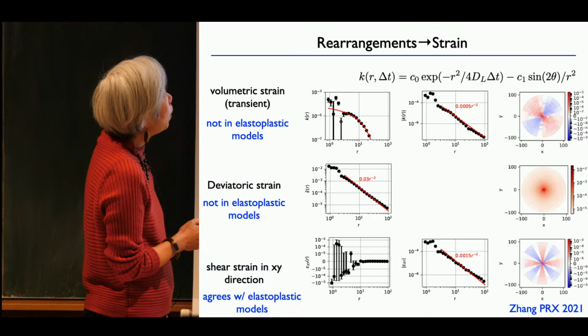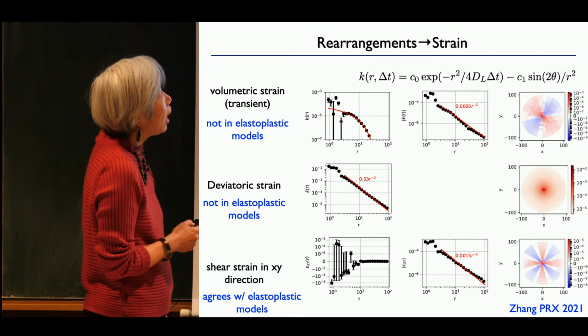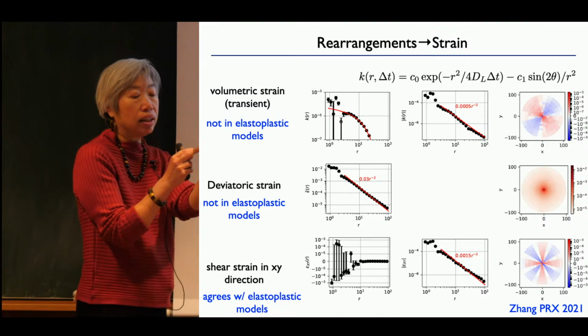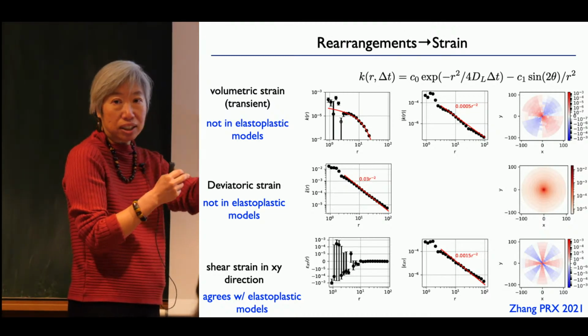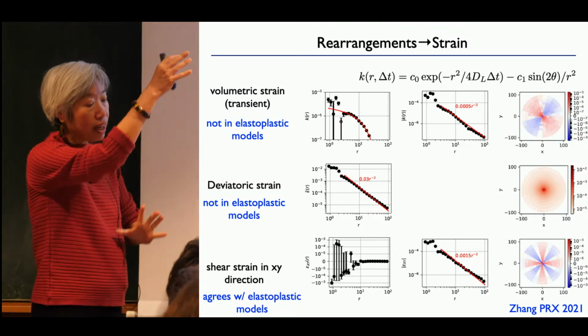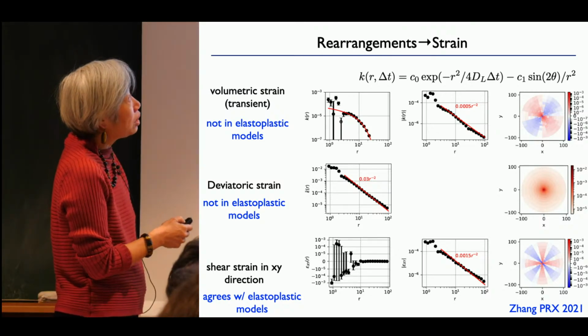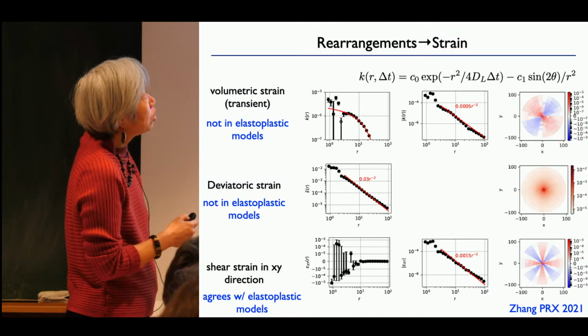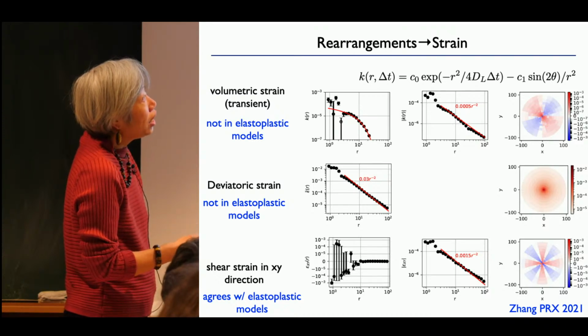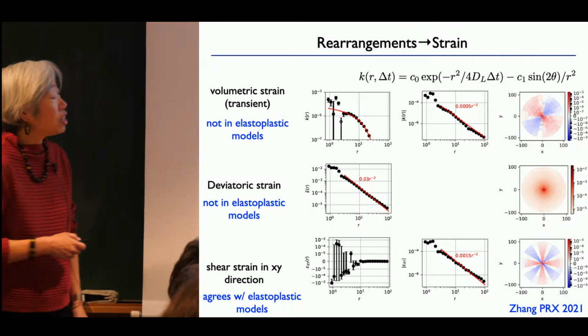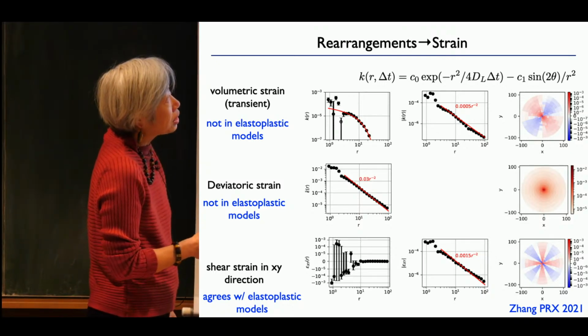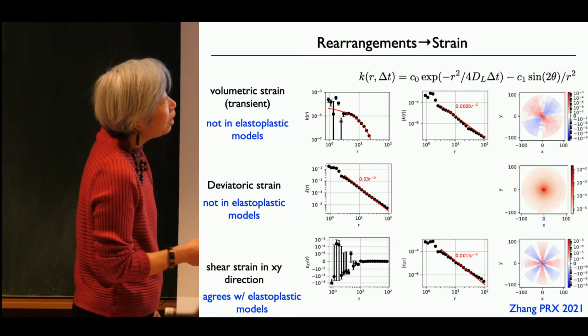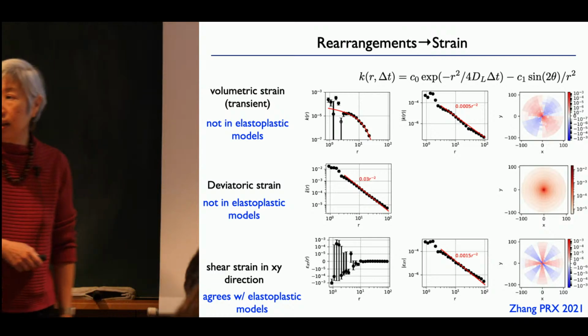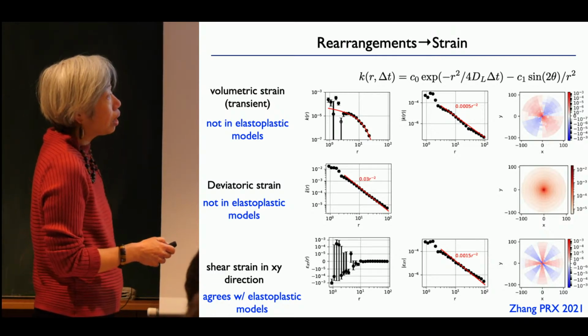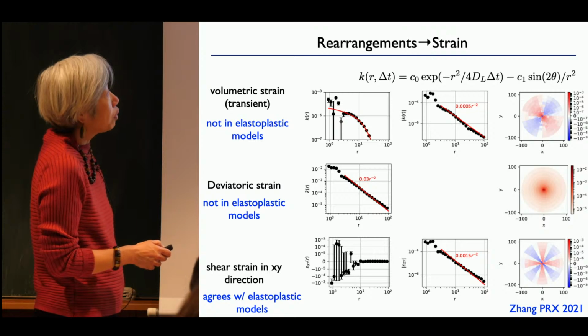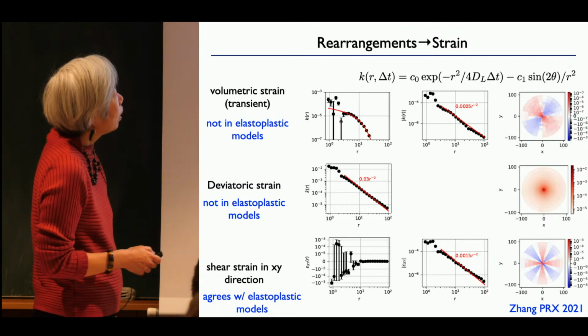All right. So what we do is we look at the strain as a distance from the rearrangement. So we take many rearrangements. This is an ensemble average, okay? And you look at the strain away from the rearrangement. You look at the R dependence, the radial dependence, okay? Both of the strain itself and the magnitude of the strain, and you look at the angular dependence, okay? And what you see is the volumetric strain has a piece that decays like 1 over r squared. This is in 2 dimensions, okay? And it has this dipolar form, stress dipolar form.